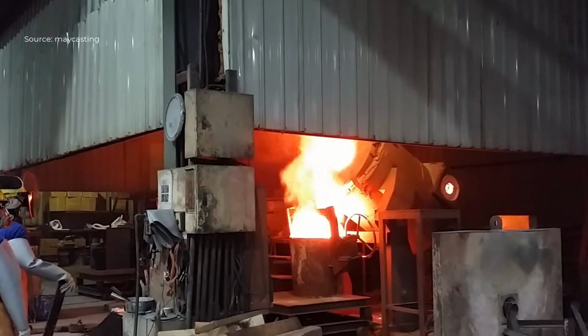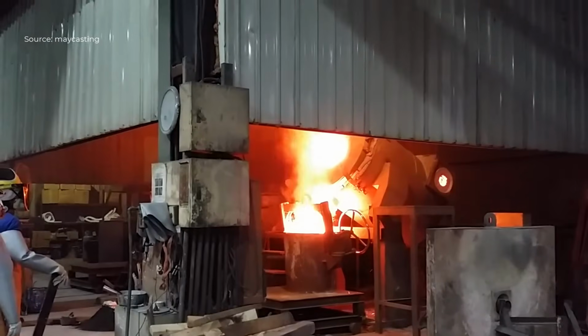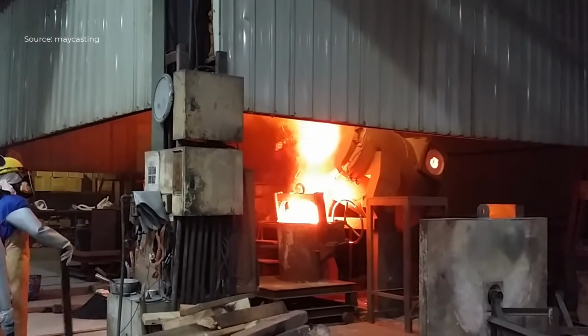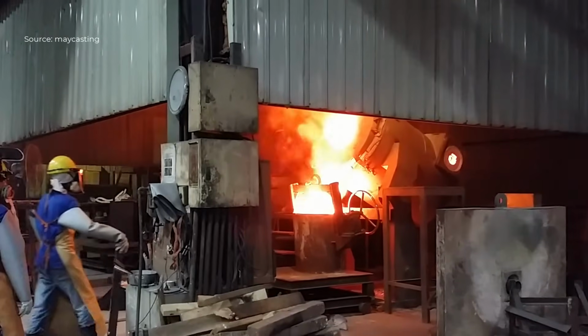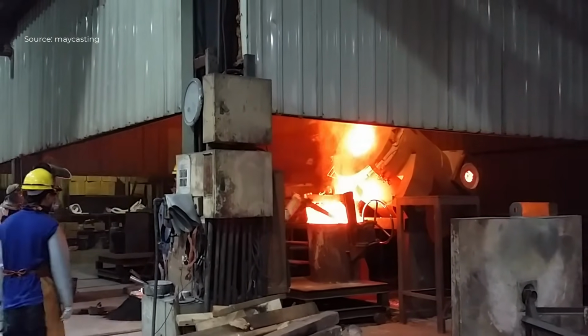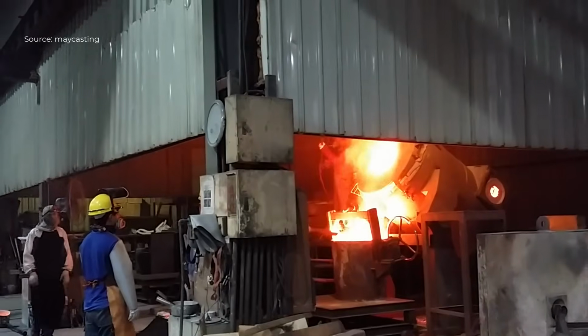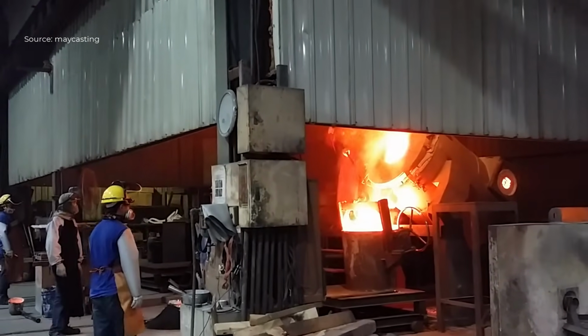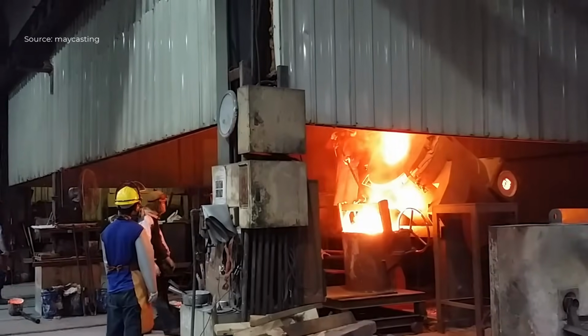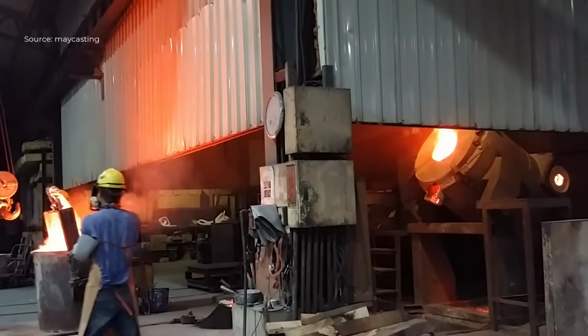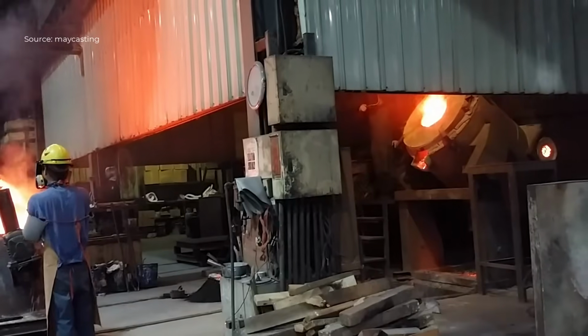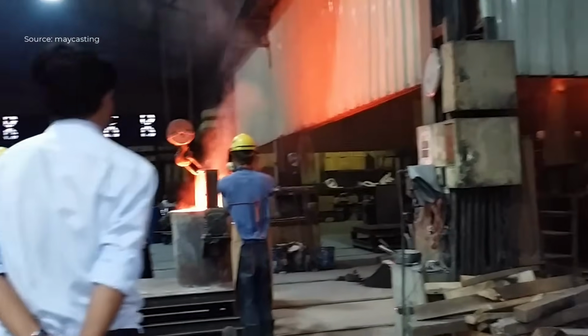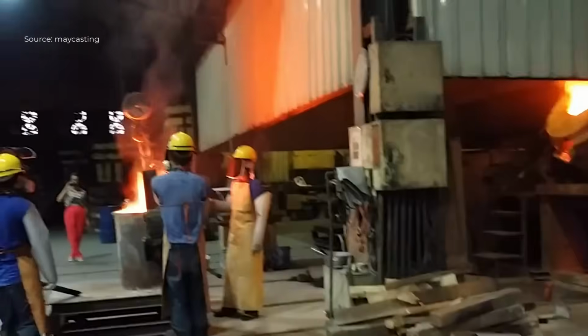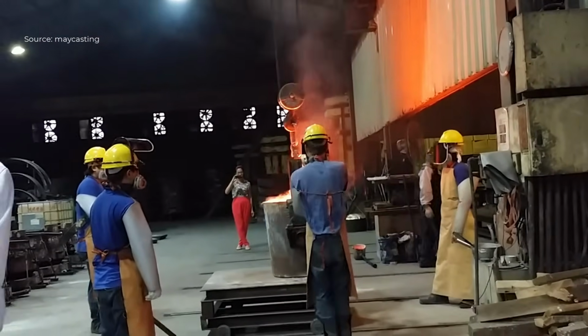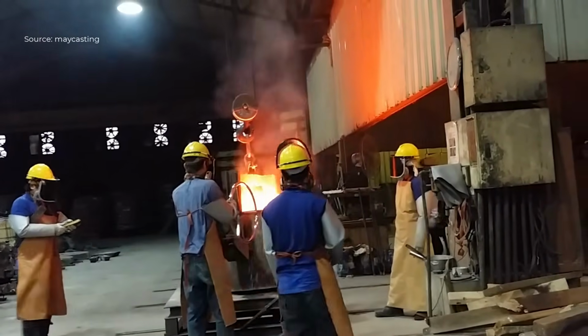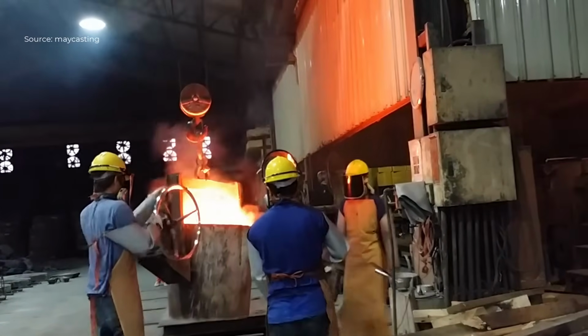When molten bronze is poured into molds prepared with green Furan, the amount of visible vapor generated is noticeably reduced compared to traditional systems. This means the casting floor no longer fills with dense fumes that obscure visibility and create discomfort for workers. More importantly, the distinct chemical smell normally associated with Furan resins is drastically minimized. Employees and visitors immediately notice this difference, as the working atmosphere feels less harsh and significantly more breathable. This improvement not only benefits worker health, but also demonstrates the company's commitment to cleaner industrial practices.